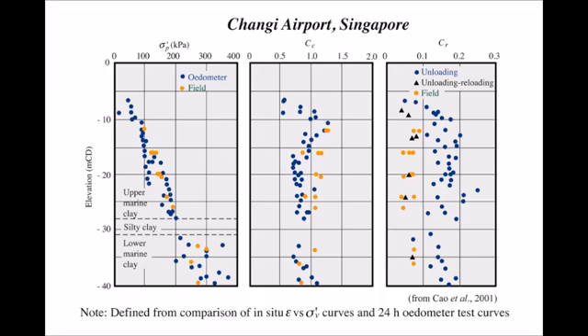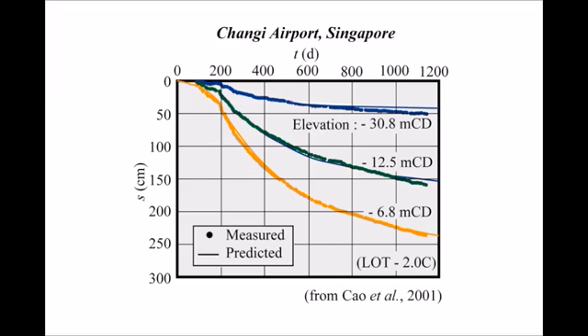And this can be shown with the case of the Changi Airport in Singapore. Here we have marine clays over about 40 meters, and it's a site which has been reclaimed. That means, in fact, the airport is built over the sea on these clays. And by considering the 24 hours odometer curves and by adjusting the permeability, they came with excellent correlation between predicted settlements and measured settlements at different depths.